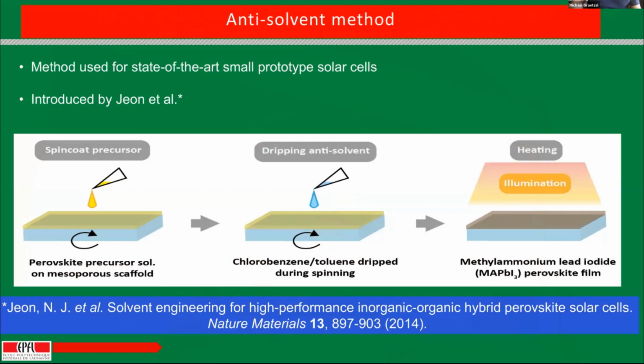And so, yeah, and then there's the anti-solvent method. The trouble, I mean, this is usually for laboratory cells, and I think the high efficiency cells, most of them, use this method. But it's very hard to scale up. I don't think it can be used in production. So if you want a good cell, you might try that, but it's pretty complicated. You have to first have everything in one solvent, and then you spin it down, and then you drip the anti-solvent, and then you heat it, and that gives you the perovskite.